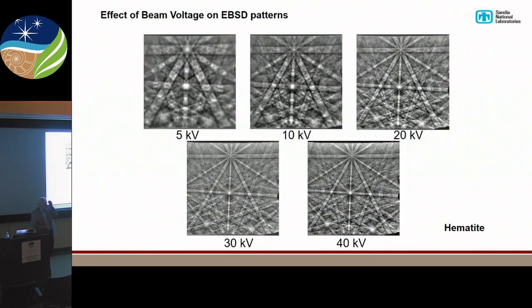Okay, so what about the beam voltage? We can do this, like I said, over a number of different beam voltages. I think this was from hematite, again purchased at my local rock shop. You can see the nice threefold axis up here. In the hematite, these are 5 kV, 10, 20, 30, and 40 kV patterns. What you notice is that the only thing that changes, and you can convince yourself of this, is the width of these bands. The positions of the zone axes don't change. So that gives us this nice stable way to measure the orientation.